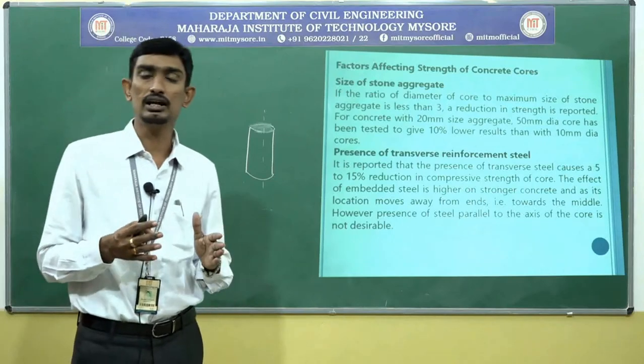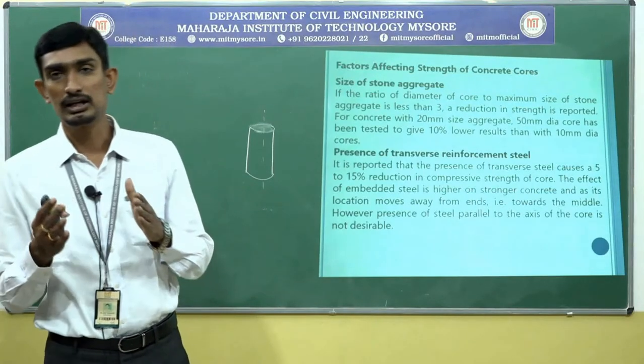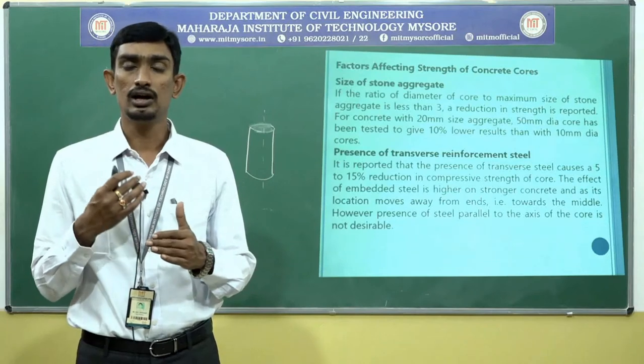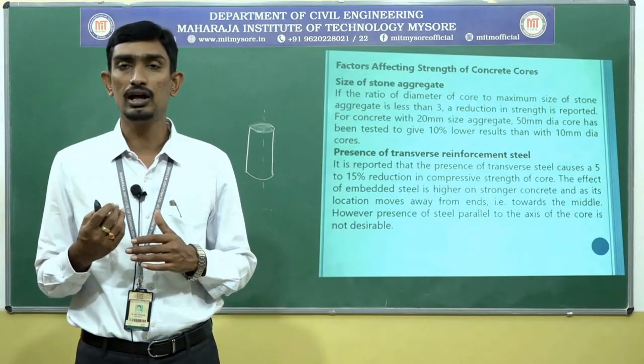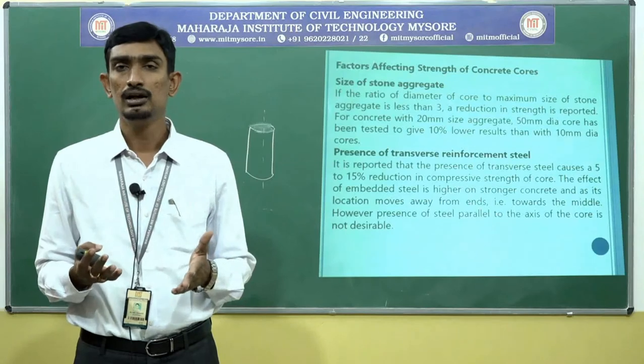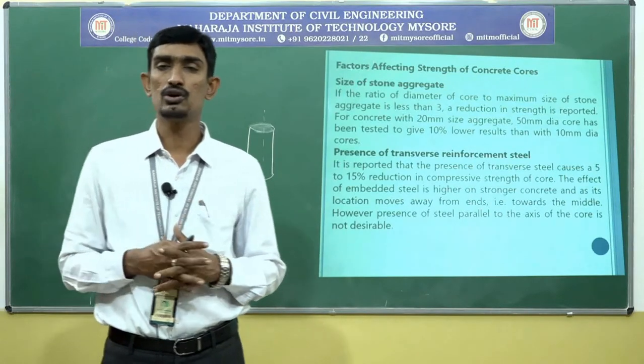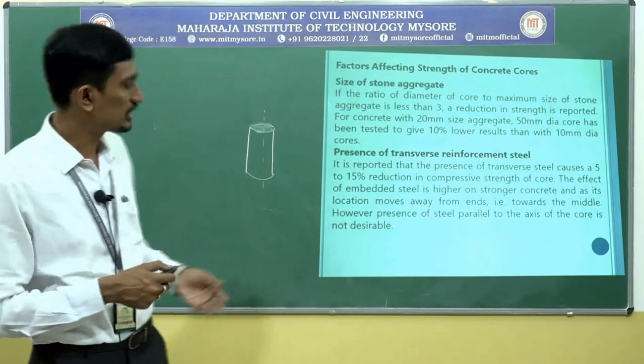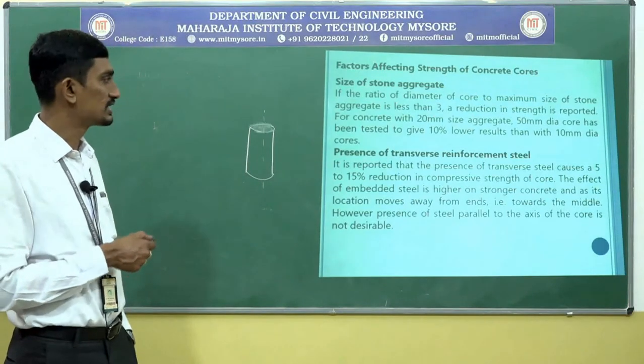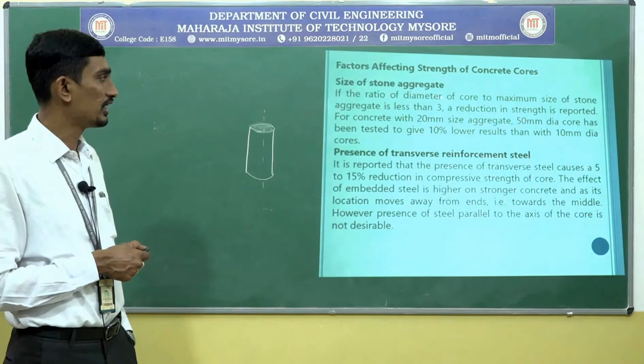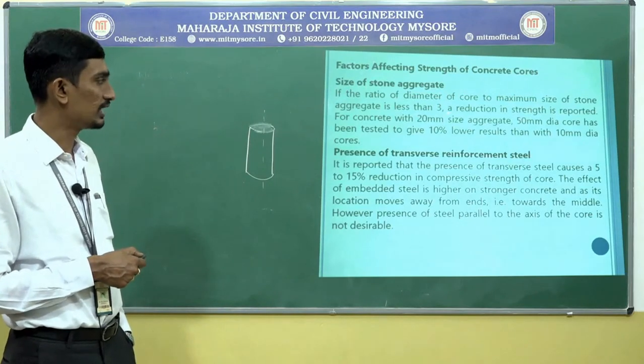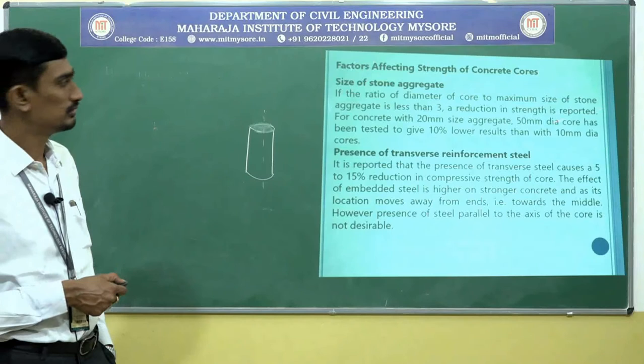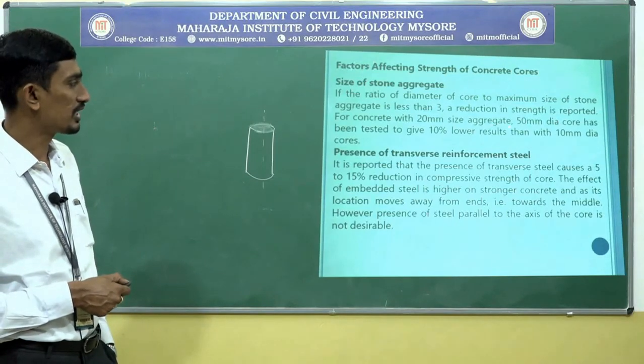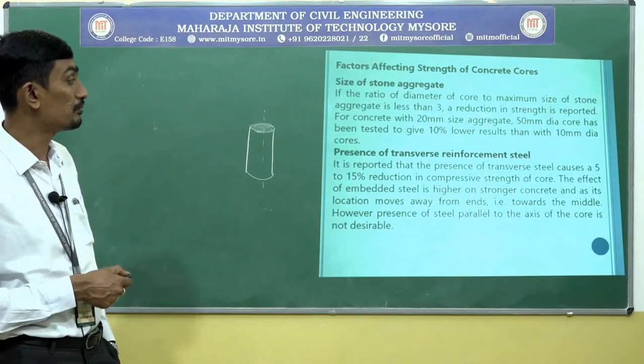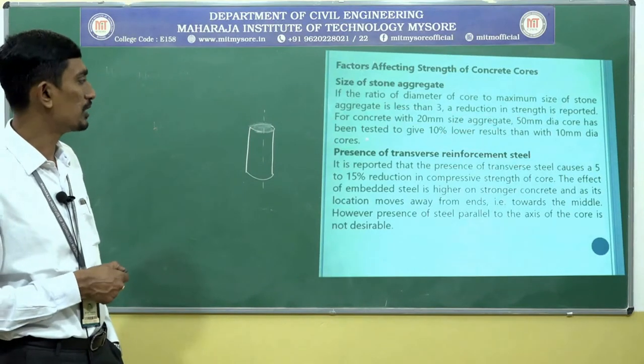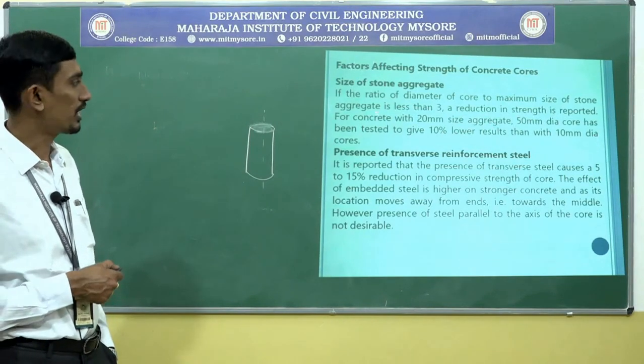Okay, so this is regarding the conditioning, curing, procuring of material, sampling, capping, and testing. This is the procedure you are going to follow. And you can see these are all the factors that affect the strength. Size of the stone aggregate: if the ratio of the diameter of the core to the maximum aggregate size is lesser than 3, reduction in strength is reported. For concrete with 20 mm size aggregate, a 50 mm diameter core has been tested to give 10% lower results than a 10 mm diameter core. So this is a factor that affects.